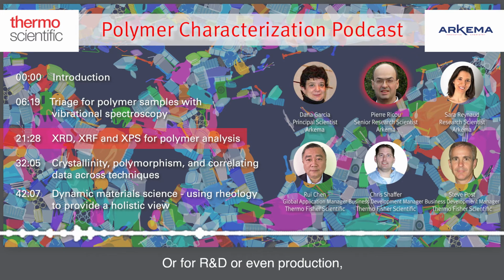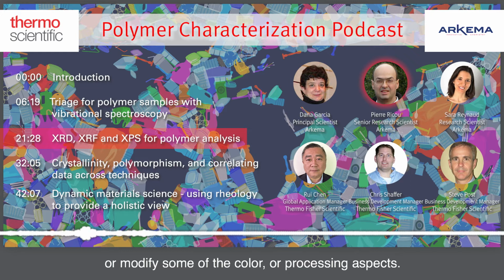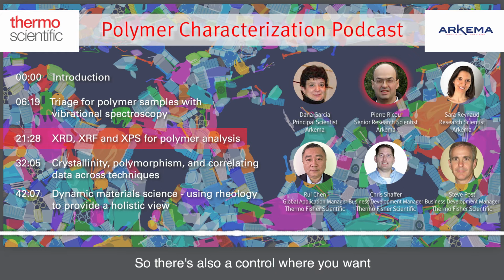Or for R&D or even production, it would also be not trace, but more additives put in the plastic to improve its property, its longevity, or modify some of the color or processing aspects. So there is also kind of a control where you want to be able to measure the different materials down to low, medium, low levels up to percent levels, depending on what you're doing with it. So it's a very, very useful technique, heavily used for us, both R&D and QC support, and also, as Dana was mentioning for the IR, often an entry-level technique in conjunction with IR, because now you can also capture all the fingerprinting, at least for the inorganic part of your material.